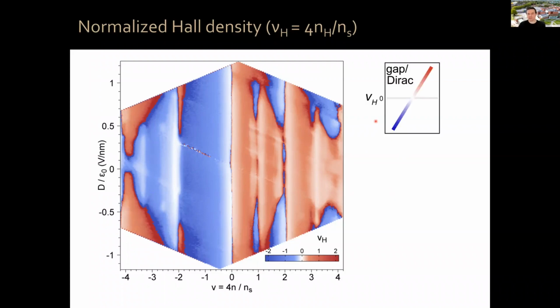In some regions in this phase diagram, you see that the normalized Hall density changes sign smoothly through zero. Okay, you go, for example, from dark blue into white, dark blue, light blue, white, light red, dark red. That's the response that you would expect at a Dirac point or at a gap. So for example, this happens here near charge neutrality. You go from dark blue, white, light red, dark red. It happens also in some of the regions.